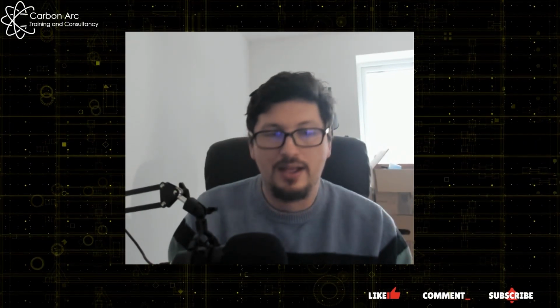Okay, so that is our sort of few questions on weldability. You can see we're always thinking about what is the effect of what I'm doing and how is it going to increase the likelihood of cracking. So if I increase carbon, I increase cracking potential. If I drop out the carbon and replace it with manganese, I'm more likely to have strength with the reduction in carbon content. So that's how we look at carbon, how we look at weldability, and how we then drive forward the changes in our process to be able to reduce cracking.